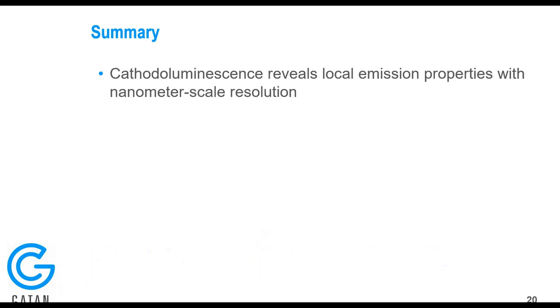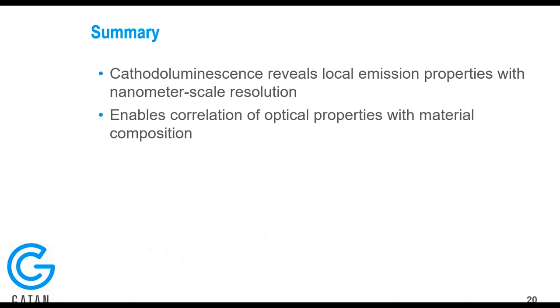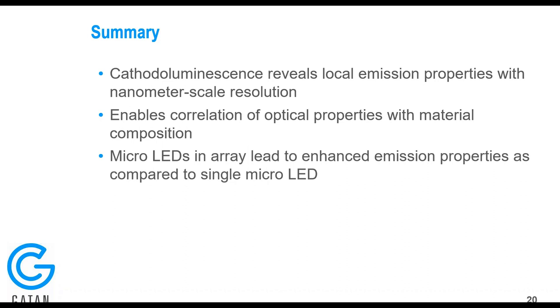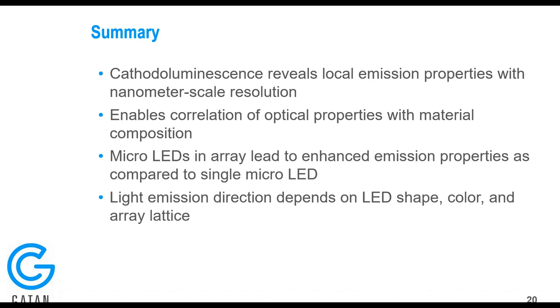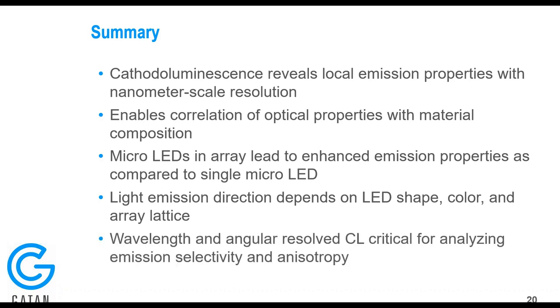So to summarize, cathodoluminescence reveals local emission properties with nanometer scale resolution. It enables the correlation of optical properties with material composition. We can see the enhancement in a micro LED that's been formatted into an array as compared to a single micro LED pillar. And the light emission direction for an LED depends on its shape, its color, and whether or not it's in an array lattice. The wavelength and angular resolved CL is critical for analyzing the emission selectivity and anisotropy in those sorts of situations.